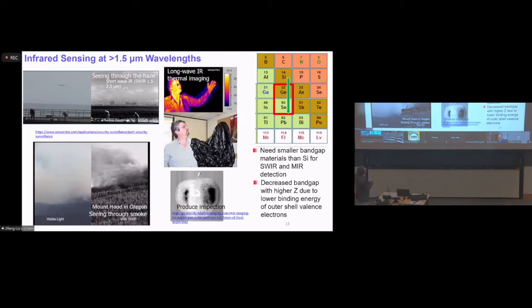So how about going to the infrared case? When you go to the infrared, the challenge you're facing is to get a material with a smaller band gap, essentially a looser bond between the valence electron and the atomic core. And as I mentioned, interestingly, you also go down the periodic table, because when you have big atoms, the valence electrons are further away from the protons and less attracted. So they're good for both X-ray, because they interact with the inner core electrons, and the infrared, because they interact with the outer shell electrons. In this case, to be compatible with silicon, we hope to use germanium tin.